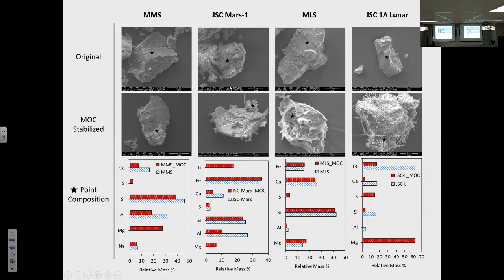And as for the JSC Mars 1, which was a volcanic ash, when you look at the original sample, you see this fluffy, very porous sort of particle, which is quite typical of volcanic ash. And we see a complete transformation when we put magnesium oxysulfate cement in it, where we saw now more sheet-like structures that have been compressed one on top of the other. And so we wanted to investigate what the composition of all of these were. When we look at composition at first glance, you can see that magnesium sulfate seems to be consistently present in all the samples that we've looked at after the treatment.